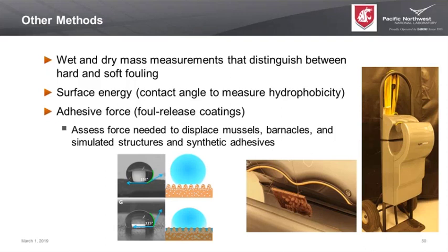Additional methods that we use, wet and dry mass measurements. We have found that by using a simple hand dryer, it's a little bit silly, but it knocks off all of the unbound water, so we get very reproducible measurements of wet fouling. And then by drying the coupons, we can get the hard-shelled organisms that accumulate. So it provides an ability to differentiate between how much mass is provided by soft organisms such as tunicates and sea anemones versus hard-shelled organisms like mussels and barnacles.